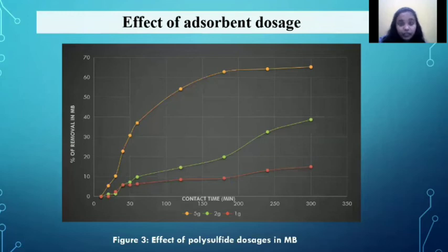We have also studied the adsorbent dosage, and we varied 3 dosages, which are 1 gram, 2 gram, and 5 gram. And 5 gram shows the highest removal efficiency. Further increase in dosage was not conducted, as 5 gram shows a constant reading after the 4th hour. That shows 5 gram is the maximum amount of polysulfide that was needed in 100 milliliters of methylene blue solution.